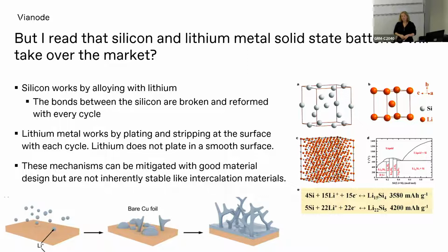But lithium metal doesn't form a smooth surface when it's plated. It preferentially tends to attach to the last lithium ion that went onto the surface, and it forms this lovely tree-like structure called dendrites. And so you can see that if you are trying to keep a nice uniform structure, and instead you're getting all kinds of little tiny trees growing up into your battery, that's not a very efficient reaction that would be stable over the long term. What you do is you form lots of extra reactions on the surface and passivation layers, and eventually you start to run out of lithium metal that is available for cycling.